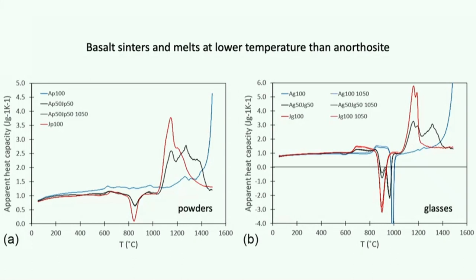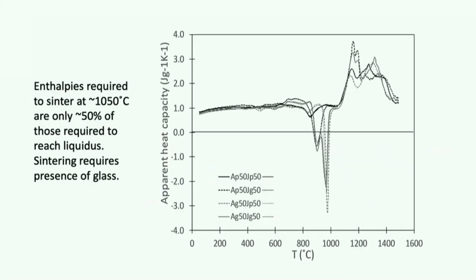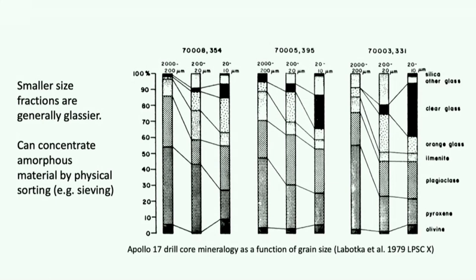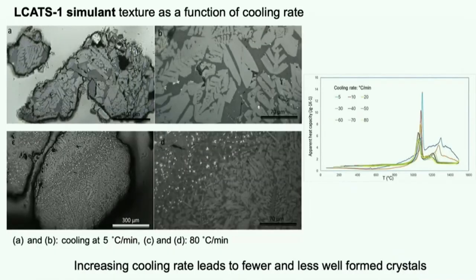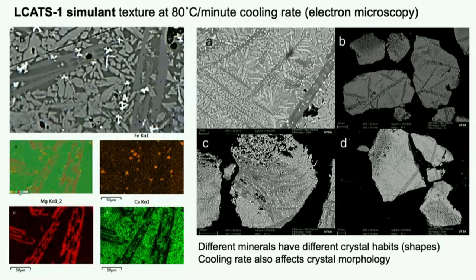It's easier to sinter the material together and form bricks at a lower temperature than the highlands. Right, the sintering to form a brick. So basically just undergoing that lower temperature crystallization, rather than completely remelting and then forming a brick and cooling, uses a lot less energy. So skipping ahead, the lunar regolith and the small size fractions are glassier. And so actually, if you want to make bricks on the moon using the least energy possible, you should sieve the regolith, take the small size fraction, it's going to be glassiest, and that'll help you make bricks as cheaply as possible. All right, so we'll skip over some crystallization stuff here.